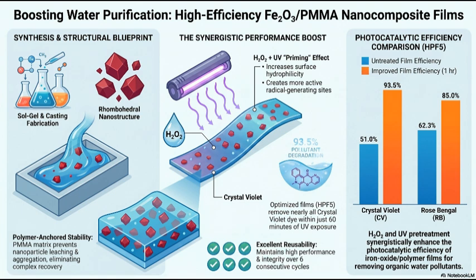The data shows that the untreated HPF5 film, after 60 minutes, only managed to degrade 51% of the crystal violet and about 62.3% of the rose bengal. A sluggish performance caused by the inability of the dyes to penetrate the surface. But the treated HPF5 film, in the exact same 60-minute window, degraded 93.5% of the crystal violet and 85% of the rose bengal. They tracked the speed of the reaction, and it followed a Langmuir-Hinshelwood simulation.